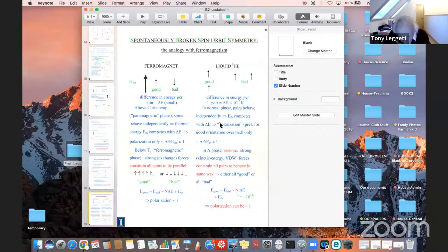For those superconductors, the usual belief is that the formation of Cooper pairs, and the maximum temperature at which this happens, is determined by the competition of the bare Coulomb repulsion between electrons, which never favors pair formation, but that can be overcome by the virtual attraction generated by exchange of virtual phonons, virtual lattice vibrations. And so what determines TC, or indeed what determines whether superconductivity occurs at all in a given metal, is this competition between the Coulomb repulsion and the phonon attraction.